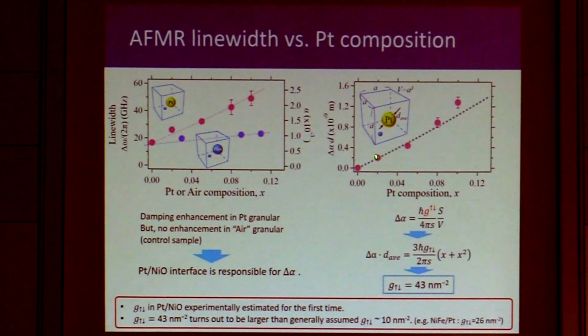So in order to model our sample, we come up with a very simple model where we have a spherical platinum particle in the nickel oxide. By using this model, we can rewrite this S over V in terms of the average diameter of platinum and also the platinum composition X. By fitting our data, we get the mixing conductance to be 43 nanometer^-2.